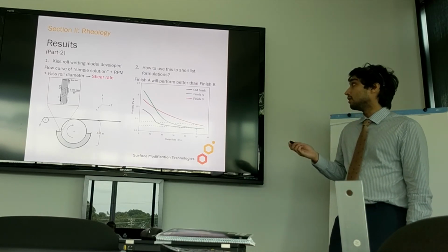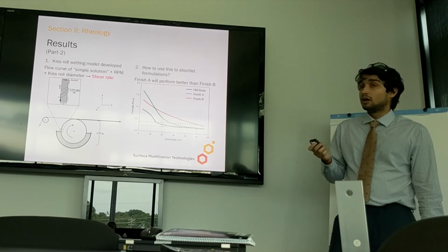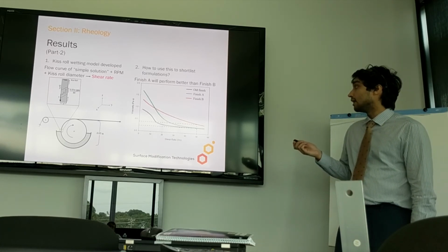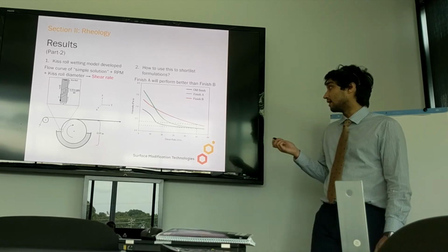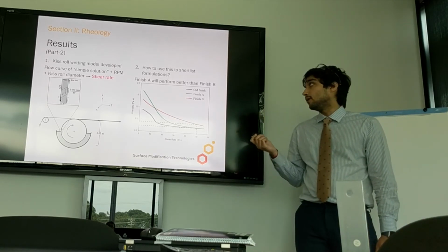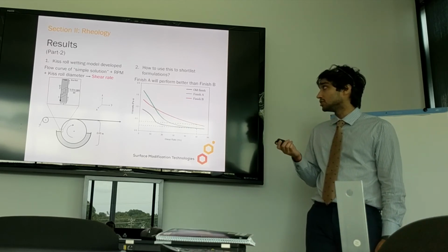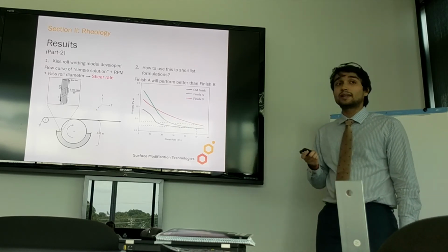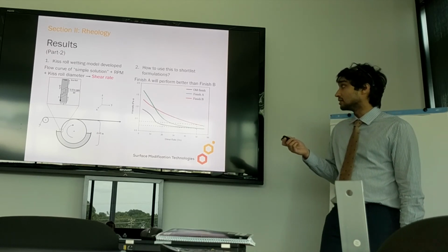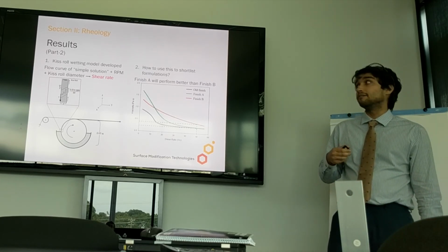For example, in this case, we see that if the shear rate at which kiss roll wetting happens is at 50 hertz, then finish A and the old finish perform almost identically at that point as compared to finish B. However, if we had formulated finish A and finish B without having any information about their flow curves or the shear rate at which kiss roll wetting happens, then for a Brookfield viscometer, which typically measures lower shear rates, we might have recommended finish B based on it being closer to the old finish than finish A.